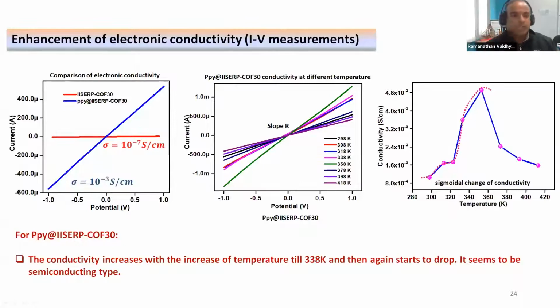Now, the most important thing is the electronic conductivity. This is the conductivity of the neat COF, which is 10 power minus 7 Siemens per centimeter. After we have loaded the polypyrrole into it, the conductivity has increased to 10 power minus 3 Siemens per centimeter, which is quite substantial. From a variable temperature conductivity measurement, we see that it keeps increasing steadily, but after 338 Kelvin, it starts to decrease again, which is a clear behavior of a semiconductor-like material. That is something we expect from most COFs, and the polypyrrole loading does not convert it into a metallic, but keeps it more like a semiconductor.